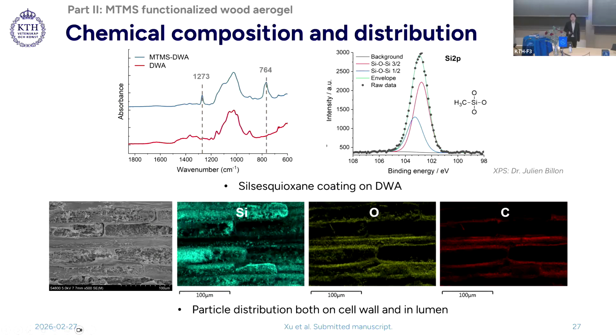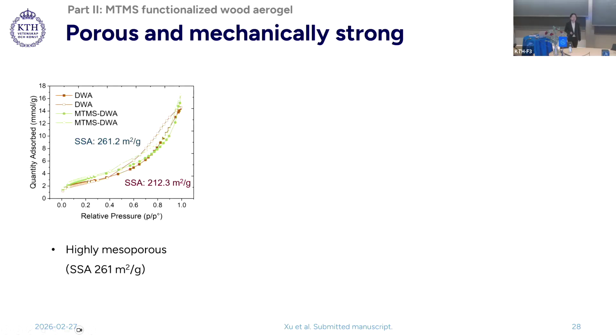Silicon mapping from EDX also confirms the wide presence of functional particles, both on the cell wall and in the lumen, showing the effective utilization of lumen space. The resulting composite shows a combination of many interesting properties. It is highly mesoporous with a specific surface area of 260 square meters per gram.